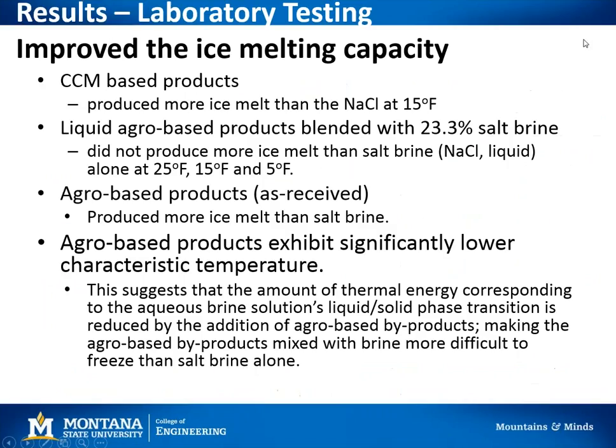So what's all this data mean? Well, for complex chloride mineral-based products, they produce more ice melt than salt brine alone, or the salt brine control, at about 15 degrees Fahrenheit. And for the liquid agro-based products that are blended with salt brine, the Category B products, they actually did not produce more ice melt than salt brine.